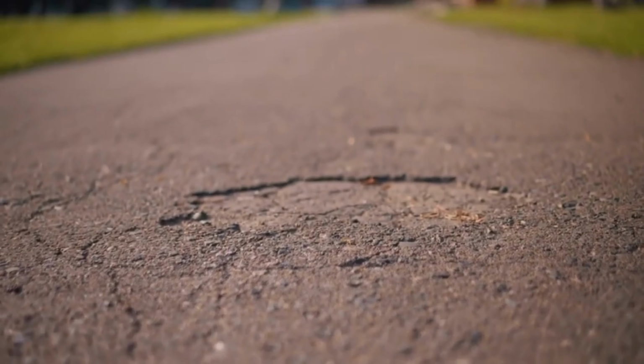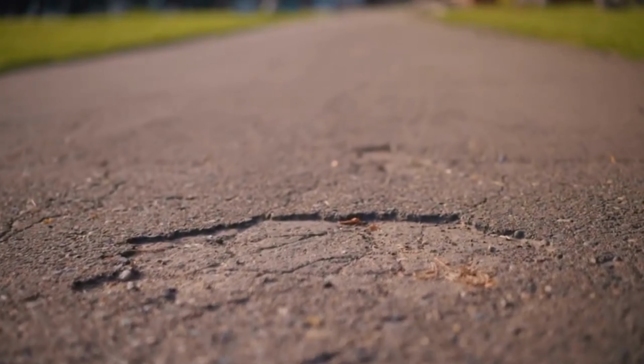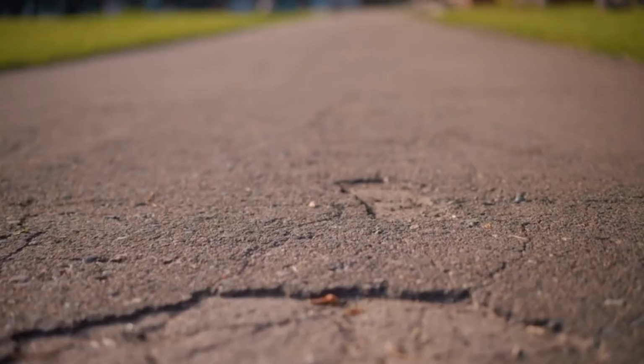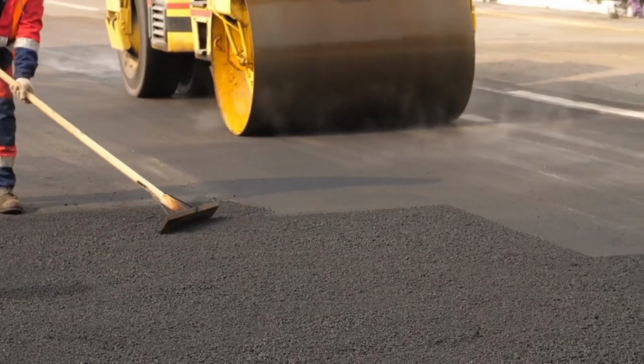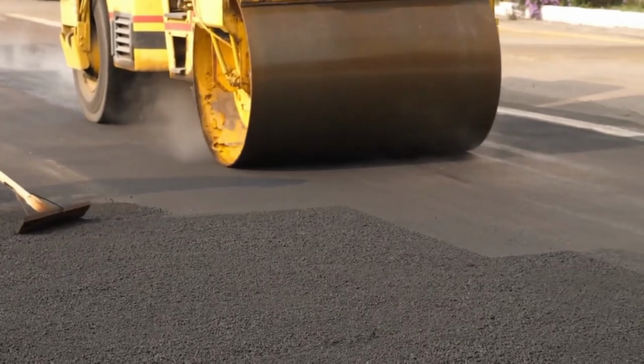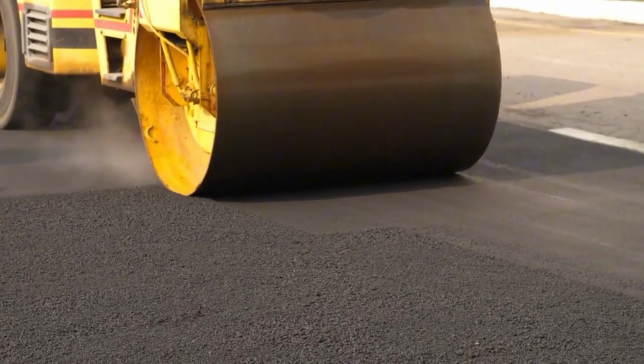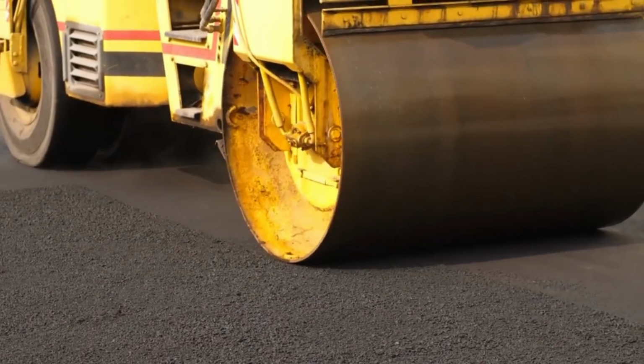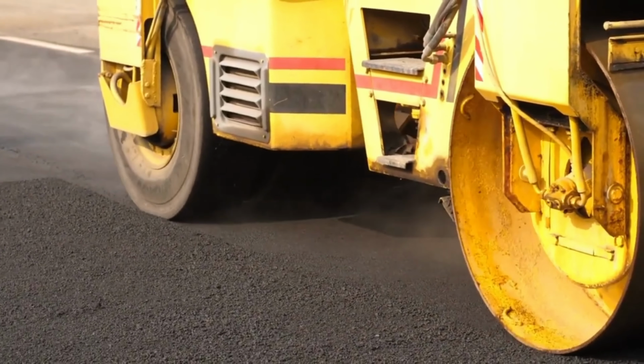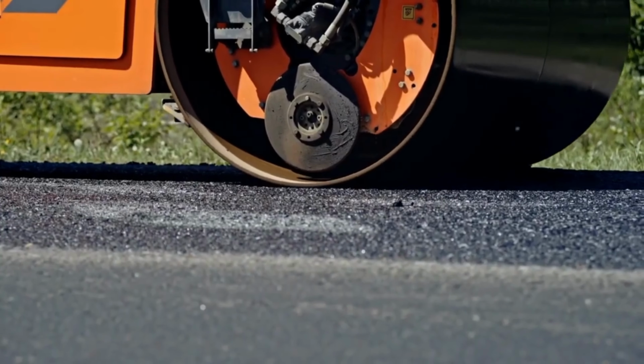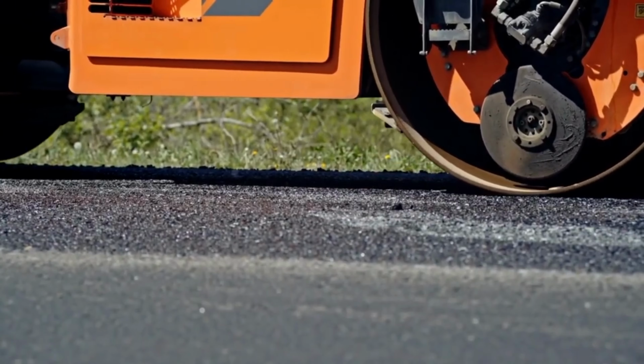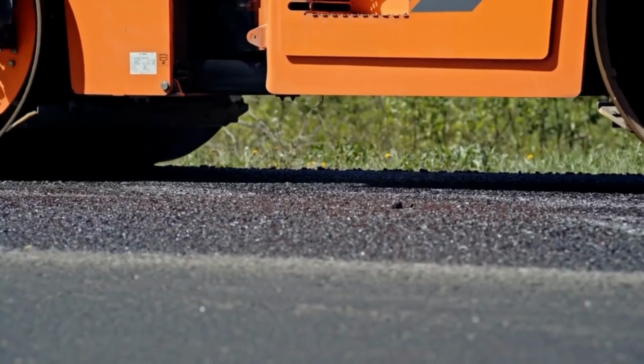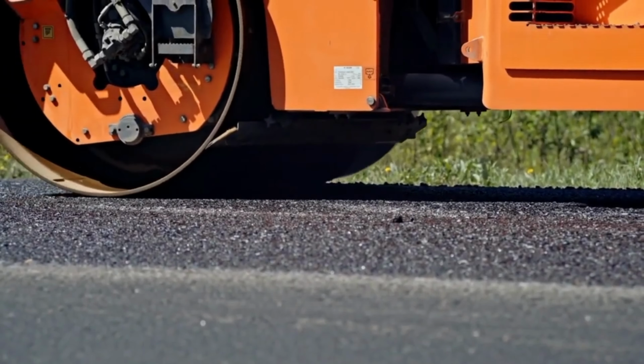Too little compaction leaves voids that allow moisture infiltration and oxidation, leading to early cracking. Too much compaction can crush aggregates or expel binder, weakening the road. Infrared sensors monitor mat temperature to guide roller operators on where and when to compact. Compaction must be completed before the mix cools below a critical temperature, typically within 10 to 20 minutes.